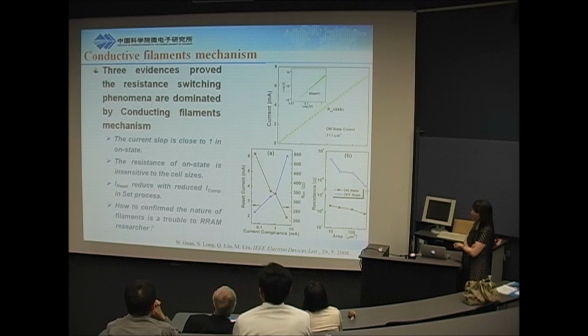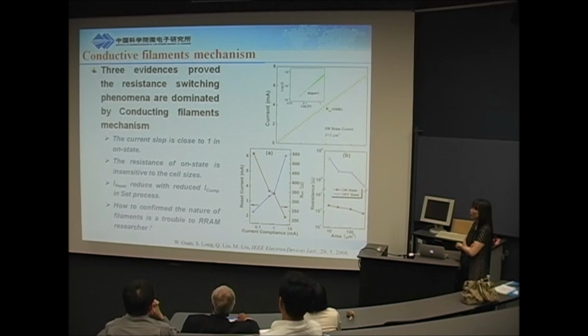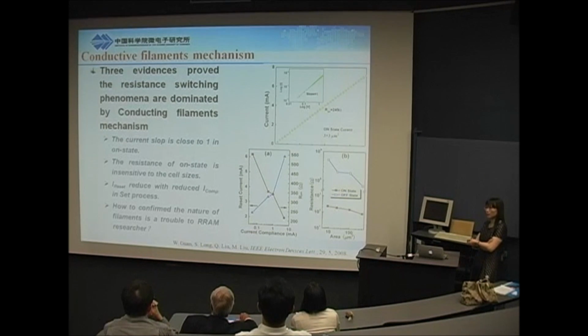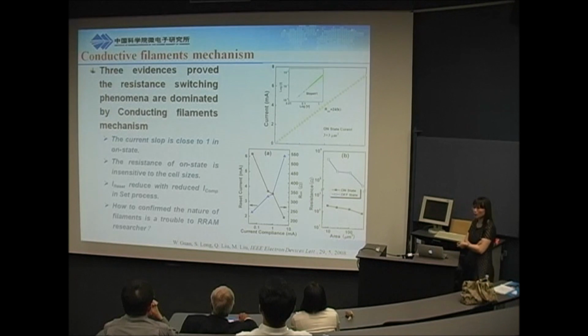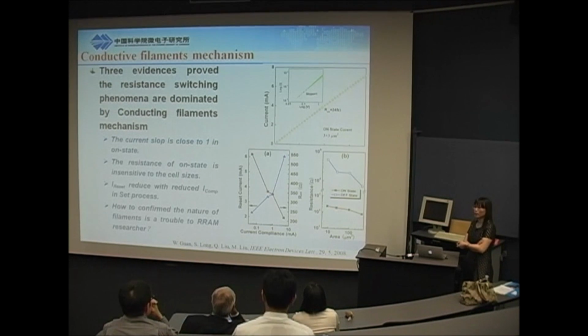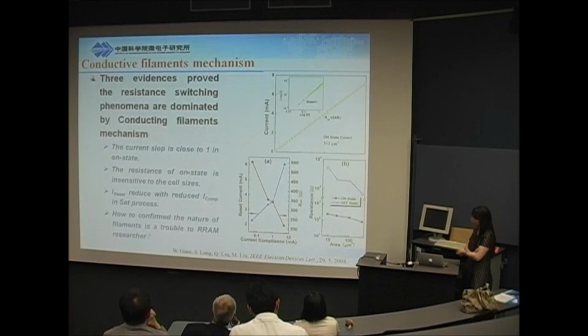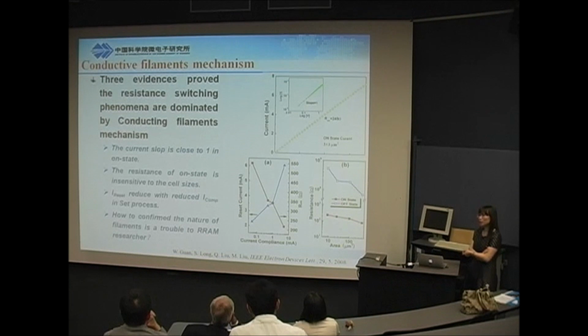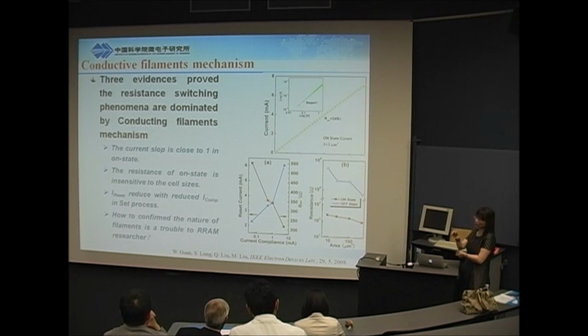Also, we can see the reset current is related to the set process. When we measure this device using a compliance current in the set process, a large one can damage the device. If you use a small compliance current, usually a very thin filament is formed, which means in the reset process a very small current can break this filament. So based on this electrical measurement, we can deduce that the switching process is due to the forming and rupture of a filament. But we cannot yet understand the nature of this filament.